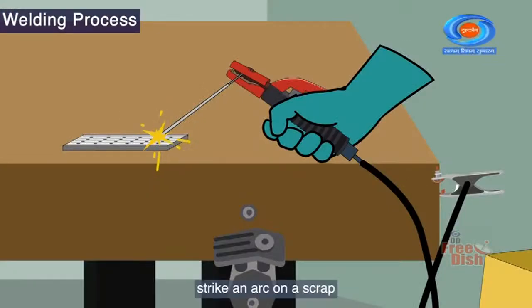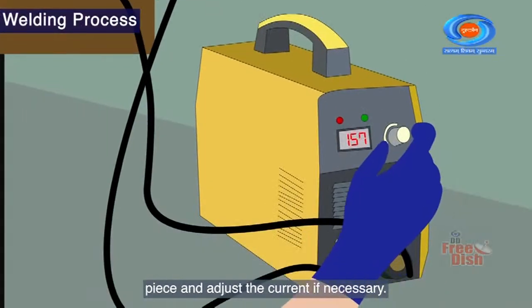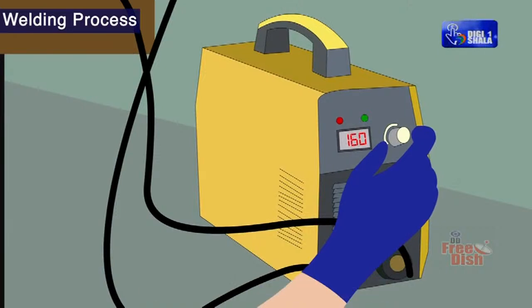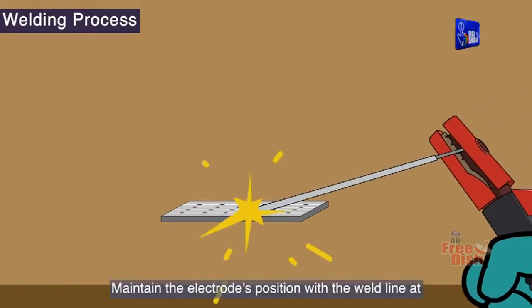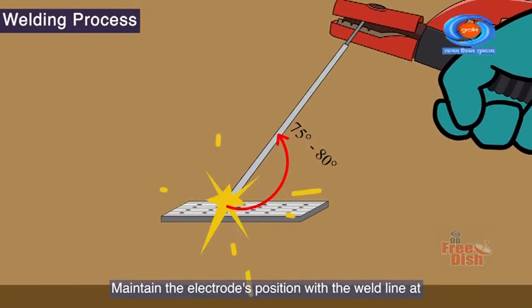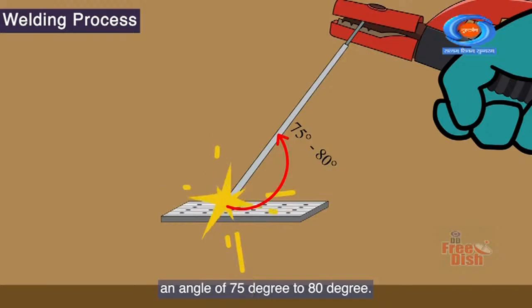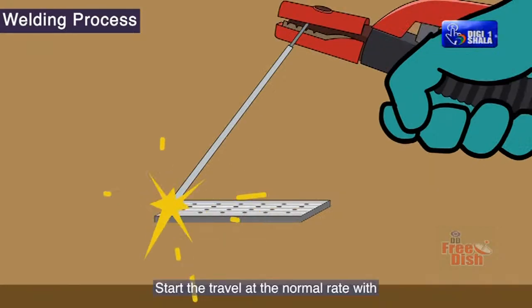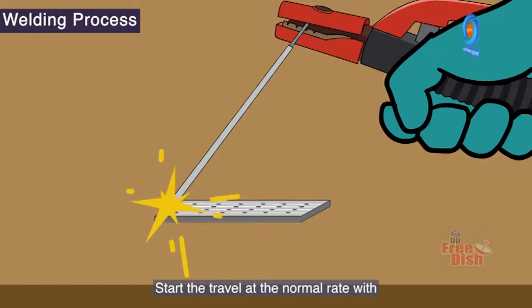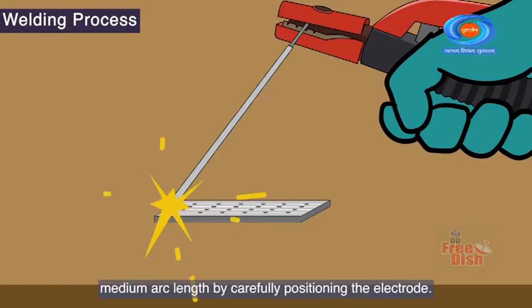Strike an arc on a scrap piece and adjust the current if necessary. Maintain the electrode's position with the weld line at an angle of 75 degree to 80 degree. Start the travel at the normal rate with medium arc length.